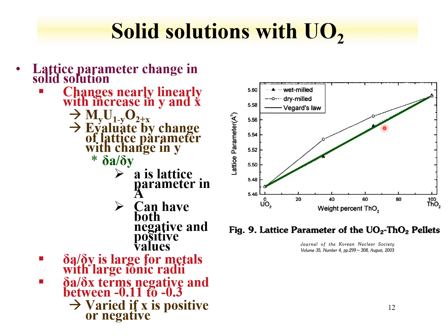We would just see that the lattice parameter, this is the lattice parameter for thorium dioxide, this is the lattice parameter in angstroms for uranium dioxide. A mixture is just a linear combination of the two. So something that's 50% would have a lattice parameter that is a contribution of 50% of the uranium dioxide and 50% of the thorium dioxide. This is a way, if one takes a compound as a solid solution and measures the lattice parameter with X-ray diffraction, you can determine the composition of both. So this linear change is Vegard's law.